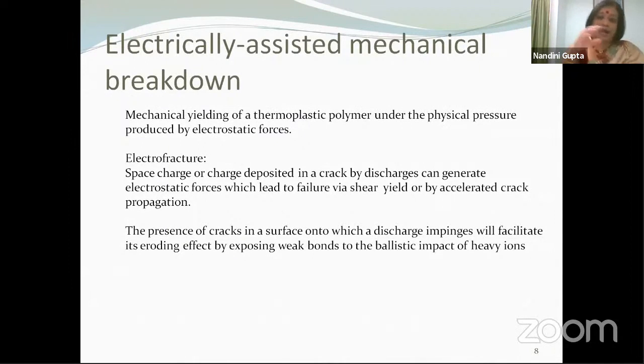Electrofracture is possible. Again, we are talking about space charge, because when you have cracks, in the cracks you have discharges, partial discharges, I told you yesterday, redistributed charges within the channel or void in which it takes place. So charge can get accumulated inside the void, and these charges can attract or repel each other and can generate electrostatic forces. So when you have electrostatic forces inside a void or a crack, it is possible to have a fracture of the material or a failure of the material through shearing processes, and this is called electrofracture.